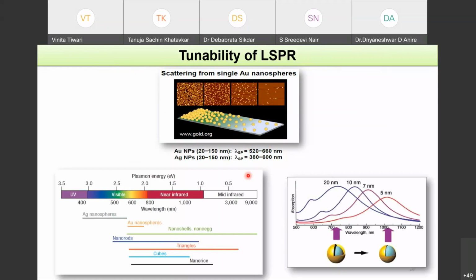If you look at other shapes other than nanospheres, like nanoshell or nanoegg, nanorods, triangles, cubes, nanorice, you can cover almost everything, starting from UV, visible, infrared, and up to mid-infrared. So that is a lot of tunability that you get from localized surface plasmon resonances. That is why they are particularly very interesting.